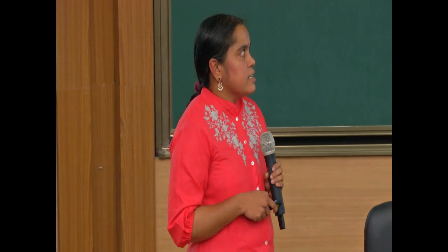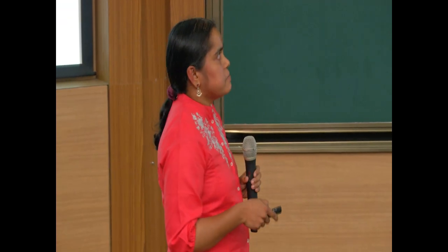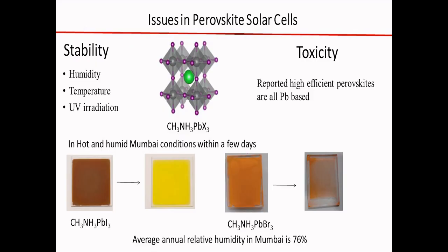But any material that is easy to make is also easy to break. So this material is not stable with temperature. If you go slightly higher than 60 degrees centigrade, it degrades, and especially it degrades even more in the presence of humidity. Humidity is something that is actually very high in Mumbai conditions, because of which this material is practically not very useful in Mumbai or places with very high humidity.